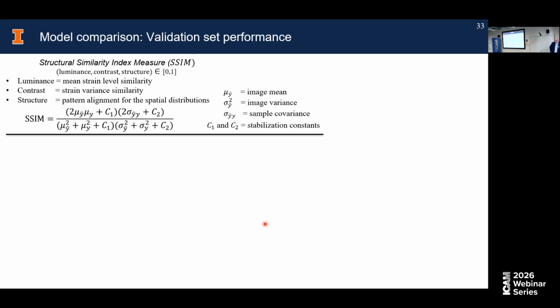what they call the structural similarity index. It really is an imaging metric, which essentially gives you a sense of luminance and contrast of the image and some of the structure or the patterns in the image and so on. And that works very well for what we're trying to do here, because luminance can translate to mean strain. Contrast can translate to strain variation. And we indeed have these strain band patterns that develop, which would be the structure of the image. And this is the definition of the SSIM if you're interested in looking at it.